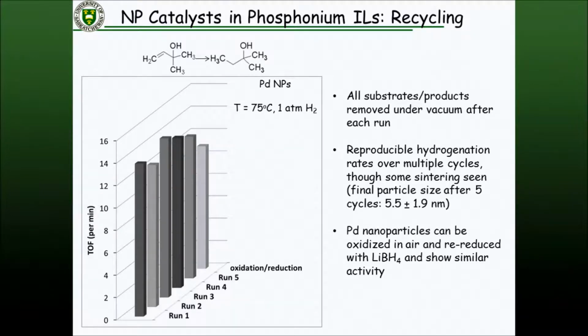This is one of the things that we really worked on, because obviously this is a drawback: our effective metal surface area is dropping over time. We found that we can now oxidize the palladium in air and then reduce it again to bring back the activity of the catalyst. This is something we've spent the last couple of years really focusing on, this idea of re-dispersion of catalyst in ionic liquid. So we start with a catalyst, we've run it for 5 cycles, it's gone to about 5.5 nanometers, and the activity has started to drop off because the size is getting larger.